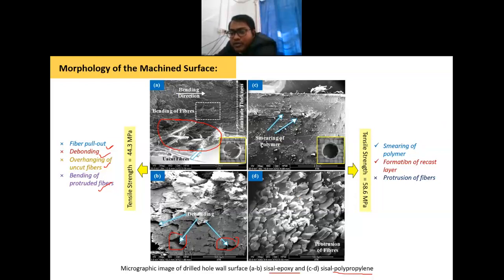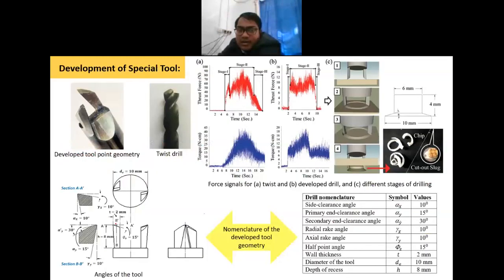Mostly it is protrusion of fibers, formation of a recast layer, and smearing of polymer. To some extent this actually helps, because when there is smearing or formation of a recast layer, it covers the fiber tip. So there will be no detrimental effect because of this; it is basically improving the quality of the machined surface. So these are the surfaces that you will obtain when you machine these materials.